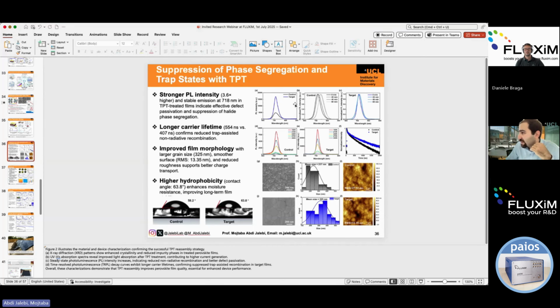This is the case actually in the control sample. You can see that over time, the PL keeps moving from a large bandgap to a lower bandgap. That means there is ion migration, and at the end, phase segregation in the perovskite happening. Once we have the target, you can see almost no changes. So, to some extent, the ion migration has been suppressed.